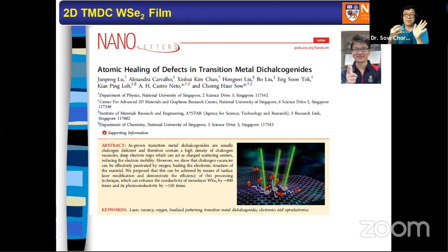Now if you use a laser beam with very careful characterization and a systematic approach, you find a sweet spot, in other words, a nice window of laser spot whereby you do not destroy the sample. Instead, you use the laser beam to warm it up a little bit, and there's plenty of oxygen supply in the atmosphere. Oxygen will fill up the vacancy. Oxygen and selenium are isoelectronic, so it can easily fill up the vacancy left behind by selenium. Lo and behold, once oxygen fills it up, the electrical transport becomes very superior compared with the pristine film, which is very bad, with a lot of potholes. So in this paper we call it atomic healing: we're using a laser beam to heal the WSe2 film.